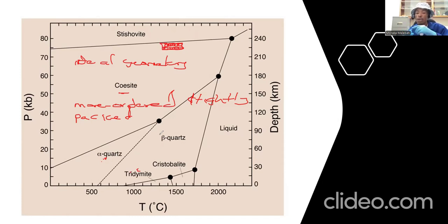Because now the atoms are energetic, they start to move, they start to expand. When they vibrate, they create space between each other. So you are making the structure open. That's why at high temperatures you have an open structure, making these silica polymorphs become less dense. That's why a high temperature polymorph is less dense than the low temperature polymorph. I hope that makes sense.